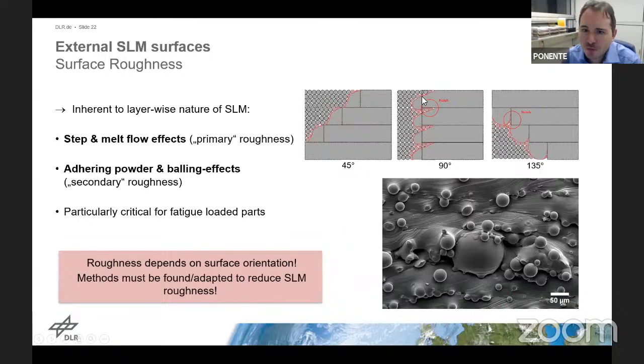If you have vertical planes, you can even have inward melting and down melting at the sides of your specimens, which can lead to this kind of notch effects or over melting. You see it here in the SEM image at the bottom, that you can discern certain layer structures from subsequent layers, and this can leave kind of undercuts. It's a very rough surface, poor surface quality actually. And if you go to downskin surfaces, so surfaces that end up over the powder bed, this inward melting of the material at the edge is actually very pronounced with copper alloys, for instance.